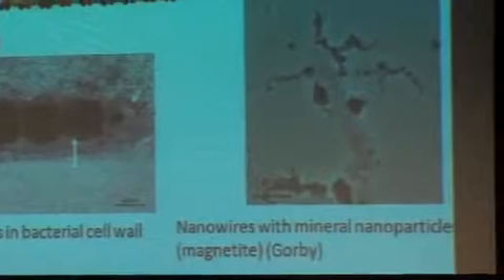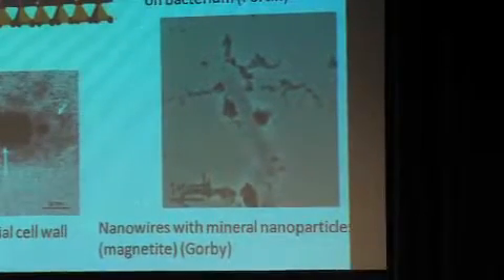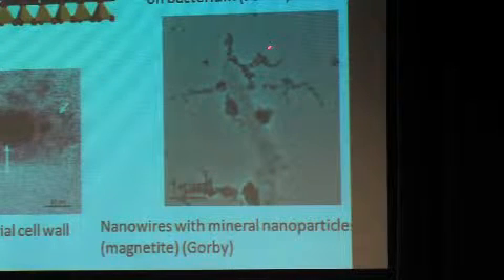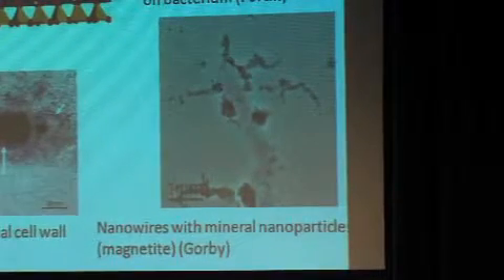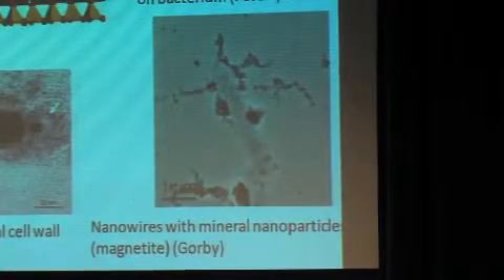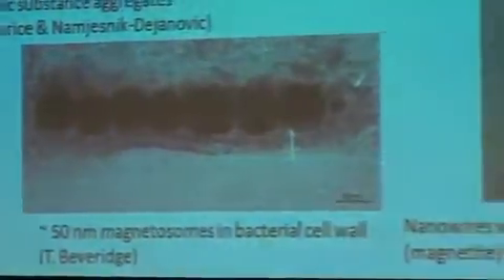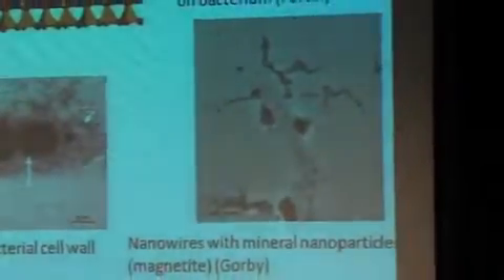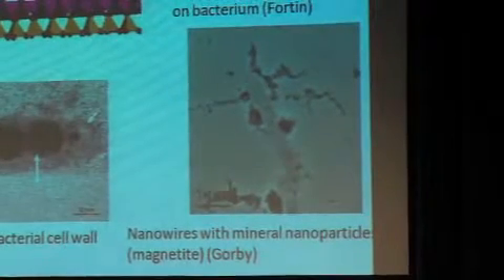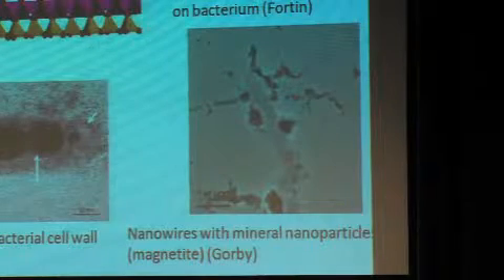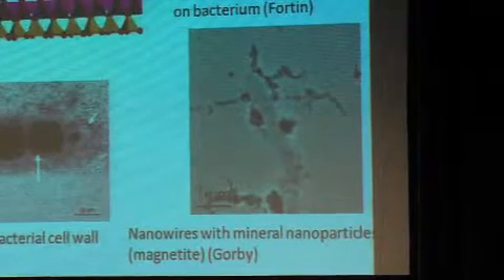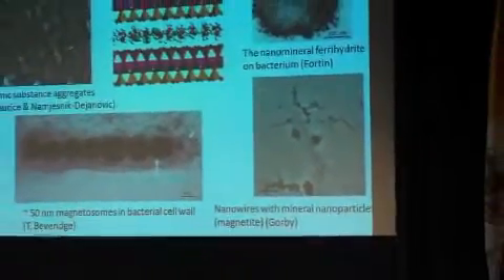Dissimilatory iron-reducing bacteria, dissimilatory metal-reducing bacteria, can have coming out of them something called nanowires. These nanowires are little wires that are exuded out of the bacteria that can transfer electrons, and you can end up precipitating various minerals or dissolving various minerals that the nanowires come in contact with because of this electron transfer. So here you've got the bacteria with these nanowires coming out from it, where you've got little iron oxides that are precipitated, in this case magnetite, because of this electron transfer. It ends up that these bacteria also can send out these nanowires and dissolve iron oxides to use for various purposes. So they can both precipitate and dissolve.